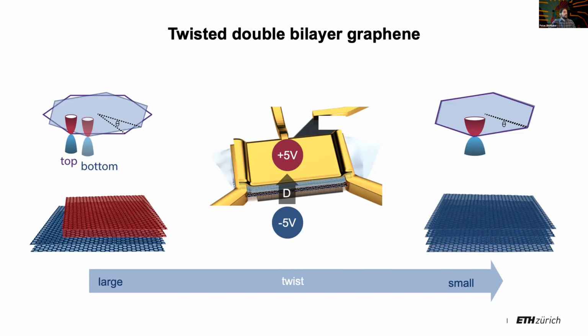So if you now draw the Fermi surfaces that you have in this regime, the two parallel lines in the Shubnikov-de Haas oscillations correspond to the K and K prime points. If you look at the Hall resistance, which is positive in this case, this leads to slopes pointing upwards in B versus n. Now these lines here, which have the slope parallel to this main density line, have opposite slope and opposite Hall resistance. So these are holes, and there's only one Fermi pocket, and that's the Fermi pocket that goes around the gamma point.